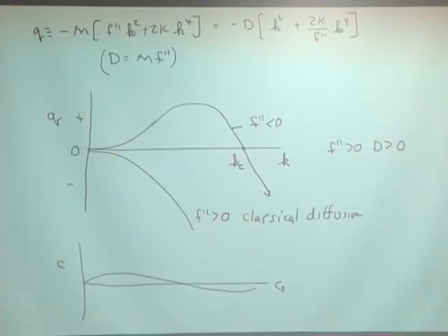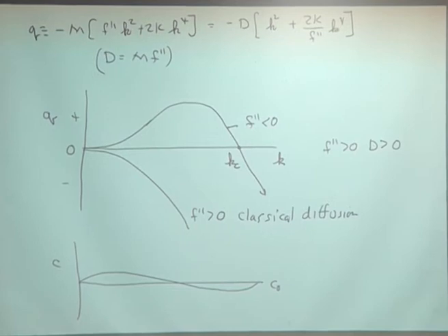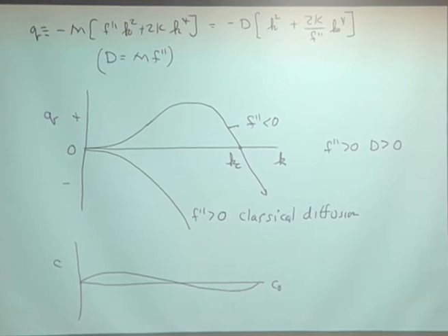So why is that? So why does this gradient energy coefficient affect these high wave number fluctuations? And the way to see that is to look at what a composition profile looks like. So that's the composition profile of a certain amplitude, certain k. And let's say you increased the wave vector, which decreases the wavelength, but it has the same amplitude, right? So you look like this.